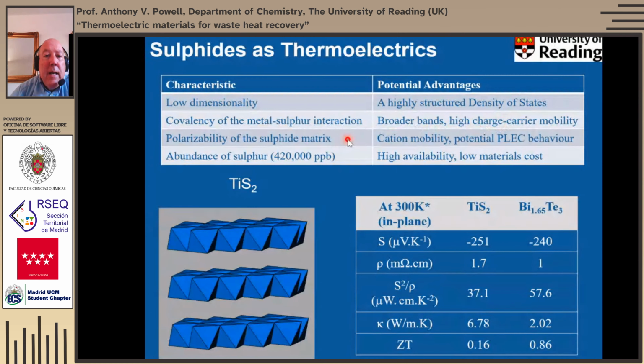carrier mobilities. It's also very polarizable as an anion matrix, so that means that we're going to see significant cation mobility and potential for phonon-liquid electron-crystal behaviour. Sulfur is also incredibly abundant, so that point I made earlier about the abundance of the materials becomes really quite important. And we were really struck by the fact that if you take TiS2, these are some data from the literature, you find that electrically TiS2 is actually quite good. It's performing in quite a comparable way to bismuth telluride.